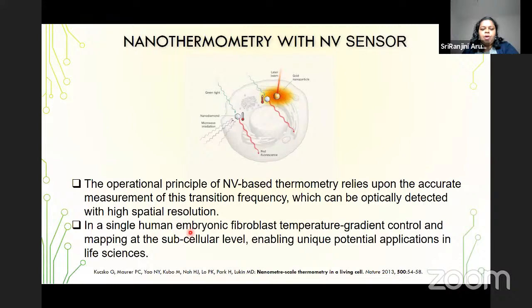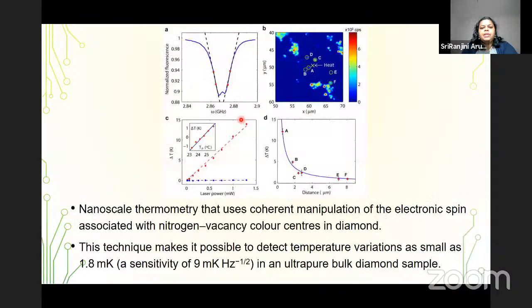So a single human embryonic fibroblast cell is taken, and in it this nitrogen vacancy center diamond is implanted. Also for control, there is one with a gold nanoparticle nearest to it, which transfers the electron. It is for control. So in this experiment, you have an incidence of green light, which is a 532 nanometer laser, and it emits red fluorescence, and then with microwave radiation you manipulate the spin states, and potentially study using this type of method.